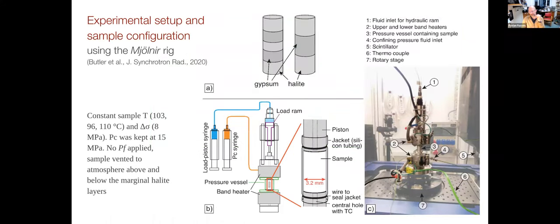So Sina spent a lot of time in our labs downstairs to make the perfect sample. These are synthetic samples. Well, the gypsum is from Italy. That's an alabaster that we core. But we wanted to make these sandwiches and succeeded in making them. So these are sandwiches. They are just under 3 millimeters in diameter and about a centimeter high. And obviously with the gypsum layer in the center and two halite layers on either side.